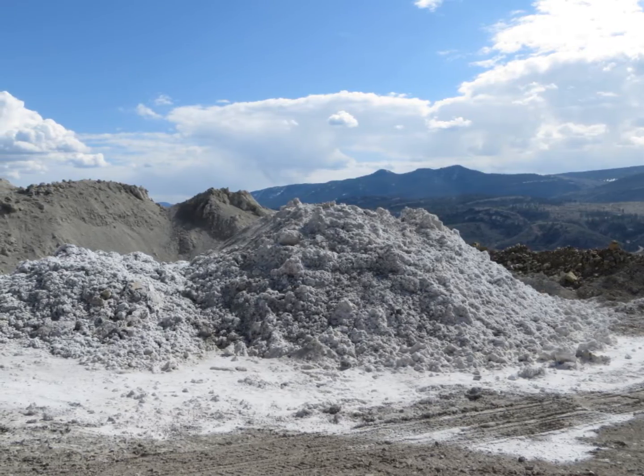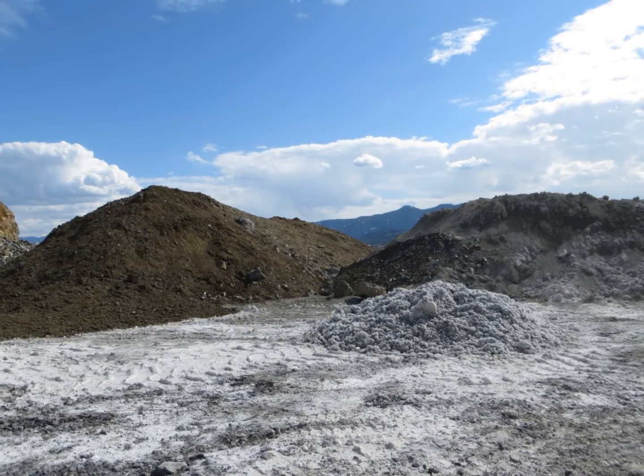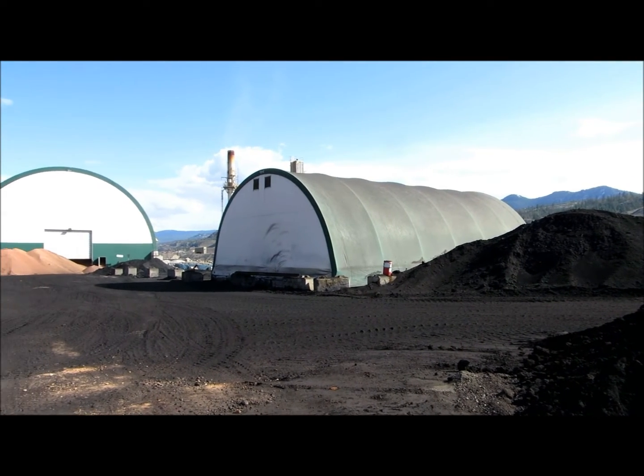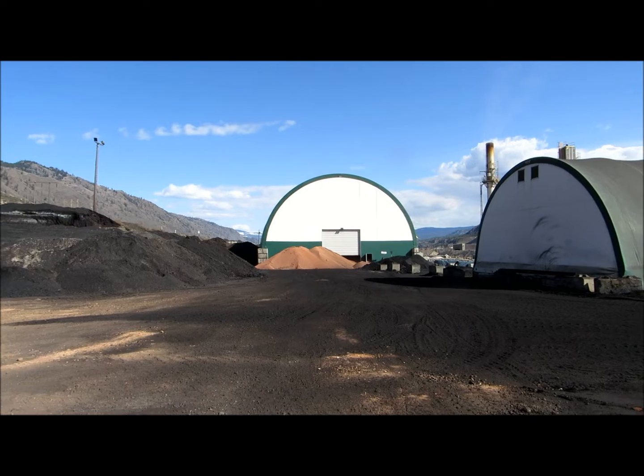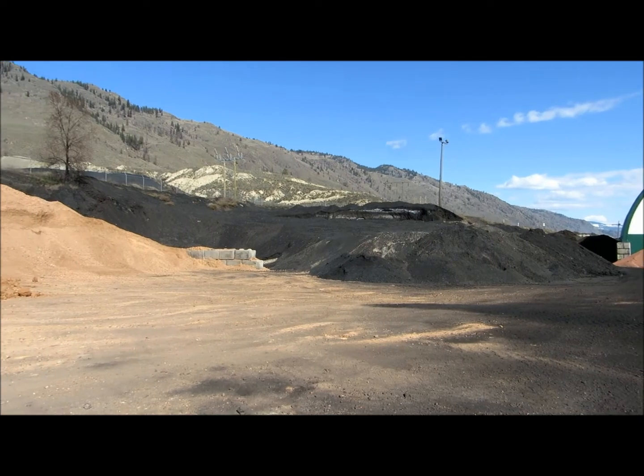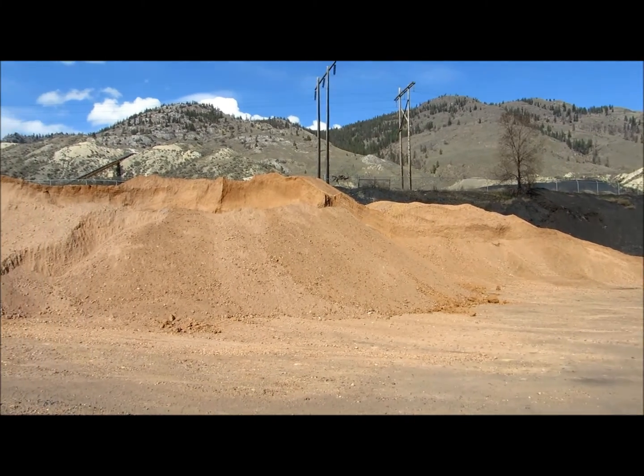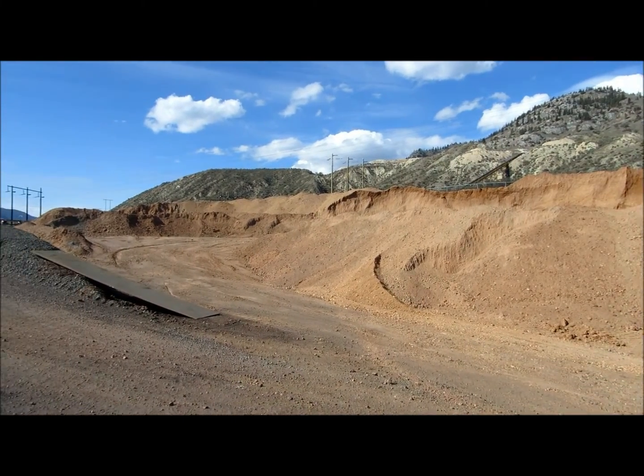The quarry is used as a source of calcium and silica, two of the basic elements of cement production. Loess clay, which is found throughout the quarry, is introduced into the pre-homogenization limestone pile to increase the alkali content. A number of raw materials found outside the plant are used as a source of alumina, such as red shale, boiler ash, fluid cracking catalyst, and spent alumina. The main source of iron for the raw materials is a byproduct of the steel industry. All raw materials are sampled a minimum of once a month to ensure a consistent production.